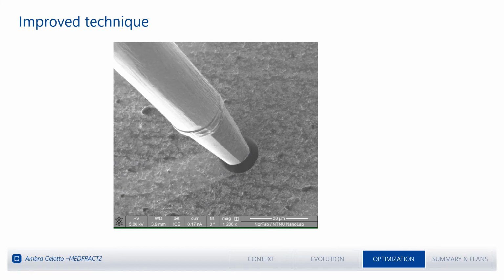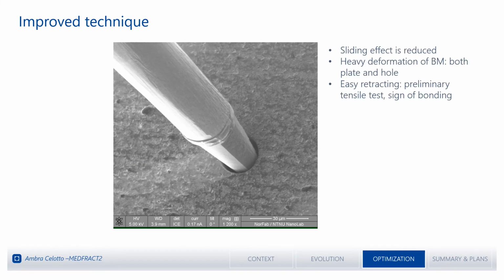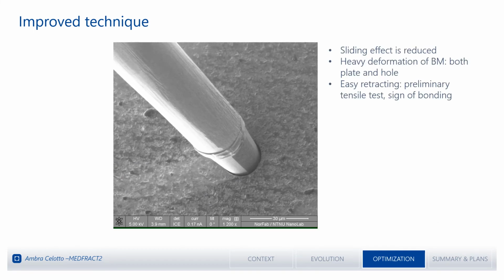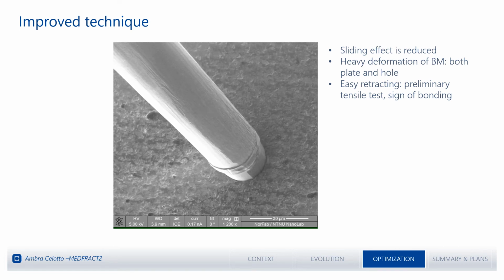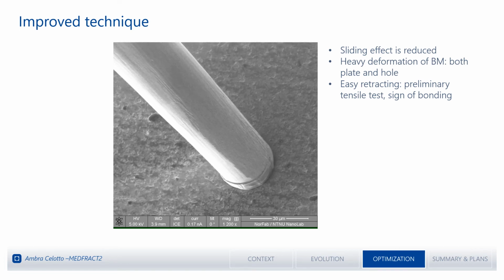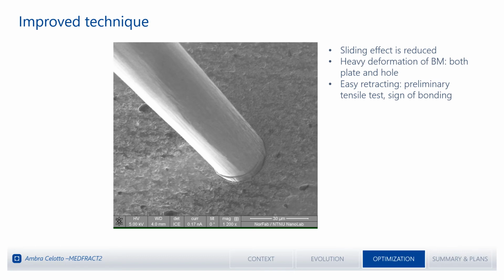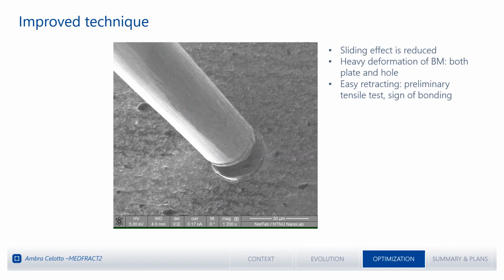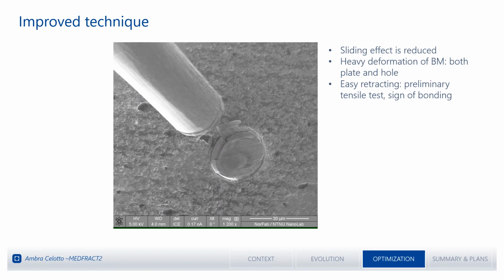So looking from the top, the welding experiment looked like this. First of all, the sliding effect of the base metal is heavily reduced. That means only a very slight misalignment between the parts was detected, and also the deformation of both parts was visible. And once again, when retracting the needle, the filler metal tip is stuck inside the hole. And this to us is quite comparable to a preliminary qualitative tensile test for assessing the bond strength.